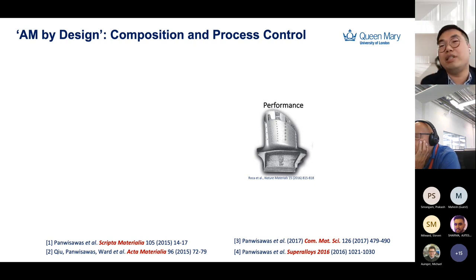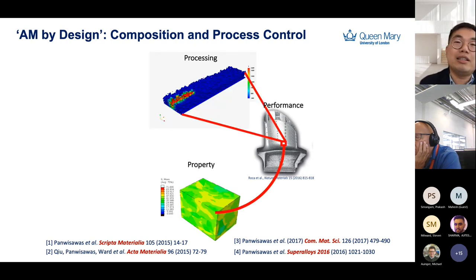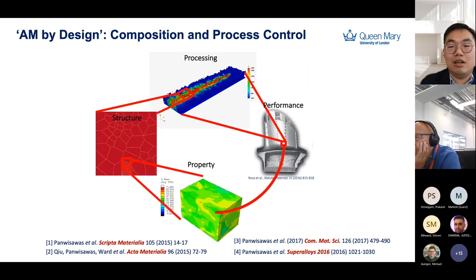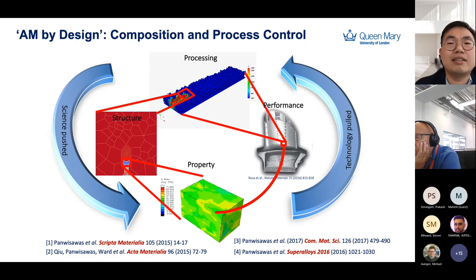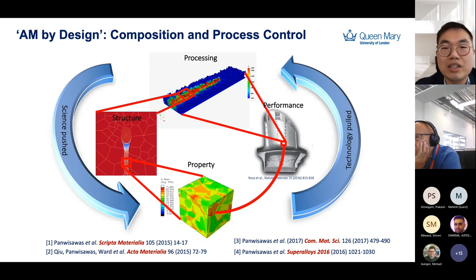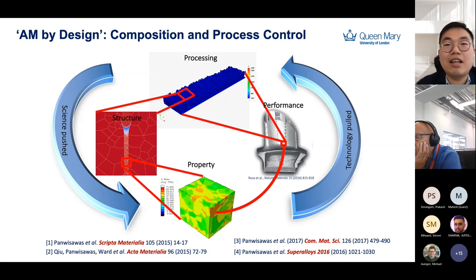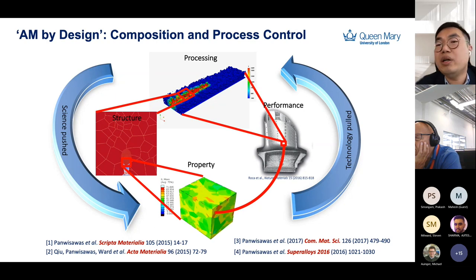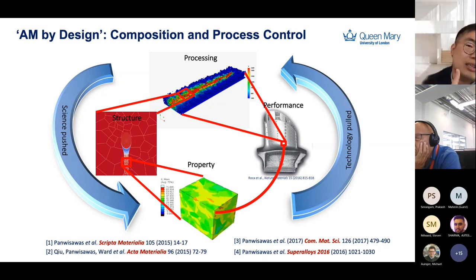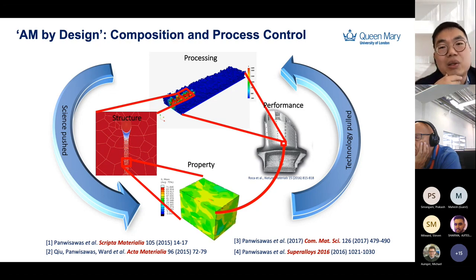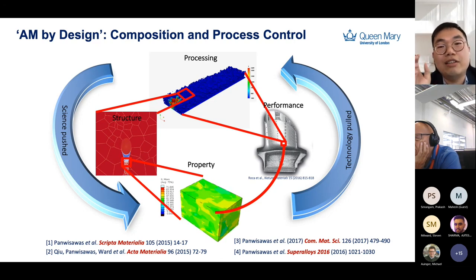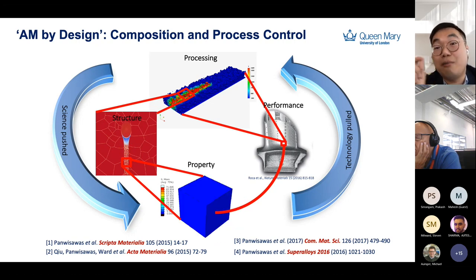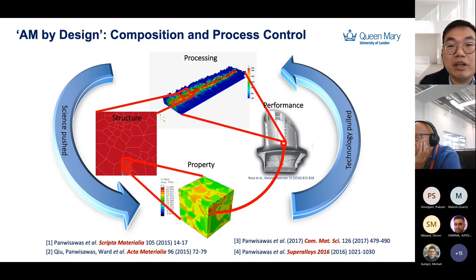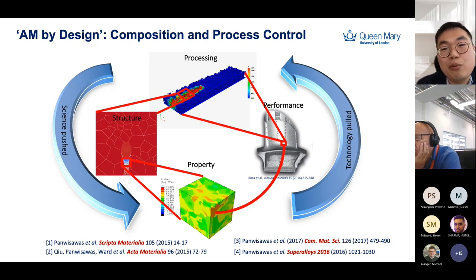So traditionally, when we want to design something, we start from what we want to get out of it in terms of the property. But for AM, we later need to understand what actually the science, or the processing science, that actually govern the property or the microstructure which emerge from this kind of process. That is quite actually a challenge, because the cooling rate, as I said, the thermal signature in this process is a rapid and repeat cycle, and that make the microstructure very unstable or non-equilibrium state, if you like. And this one has to be understood in order for us to decide further the new component or the new property that you want, in order to match with at least traditional made manufacturing process.